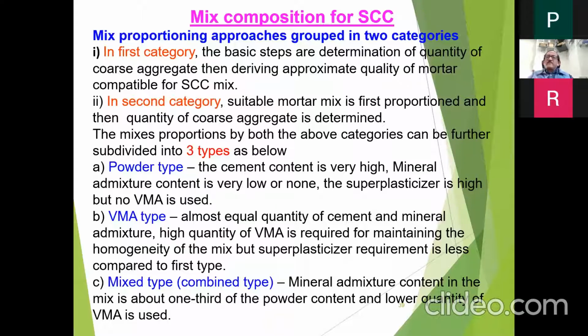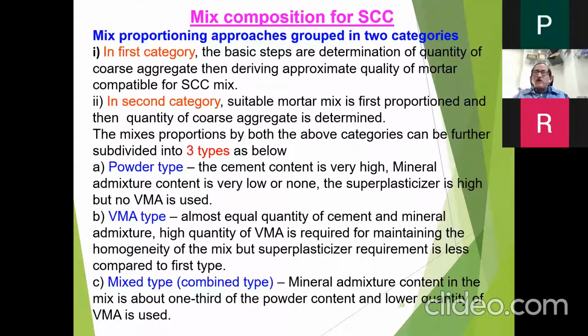And the mixes are designed, as I have talked about, in three types. One is the powder type, wherein only the powder content is much higher. Powder is not only cement, but mineral admixtures also taken together. Then the VMA type, where only VMA is used, but powder is not used. And the mixed type, that is the combined type, where mineral admixture content in the mix is about one third of the powder and a lower quantity of VMA is used. So VMA is used and also mineral admixtures are used, which would be the best type of self-compacting concrete as far as field is concerned.